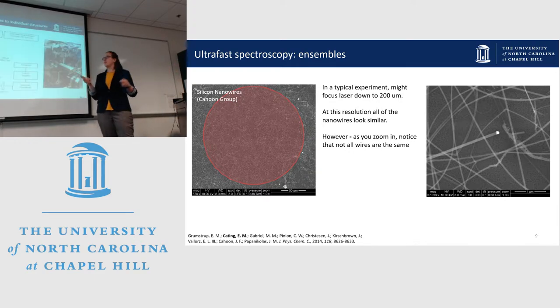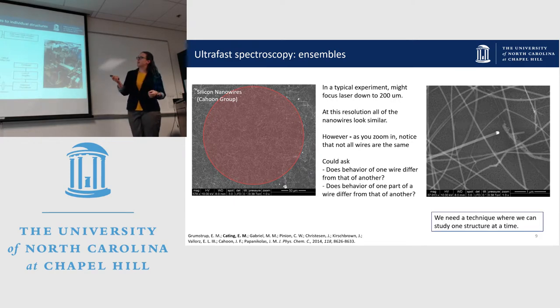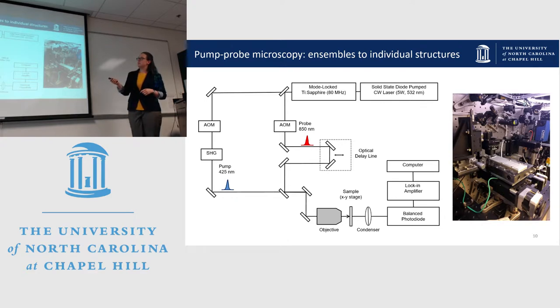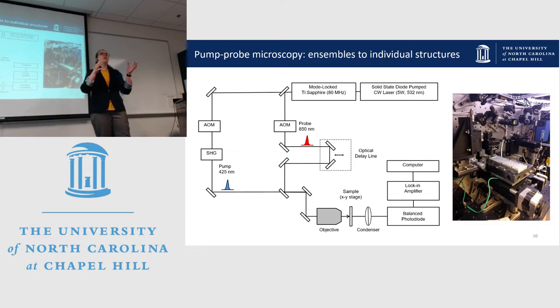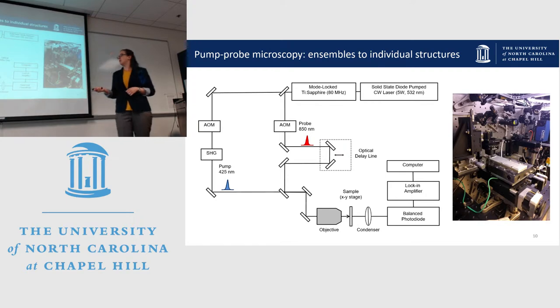And to do this, we're going to use microscopy. So briefly, the way that our microscope is set up, we have a mode-locked titanium sapphire laser. We split it into two beams. It outputs an 850 nanometer pulse. We reduce the repetition rate using acousto-optic modulators. And then the beam that's going to become our pump is frequency doubled to 425 nanometers. The beam that is our probe travels down an optical delay line. And that's just a mirror on a translation stage, which lets us change how far the probe has to travel before it reaches our sample. And that lets us change how long it takes for the probe to reach our sample. Both the pump and the probe then go through a microscope objective, get focused onto a sample, and then our probe light is collected and measured by a balanced photodiode and a lock-in amplifier.